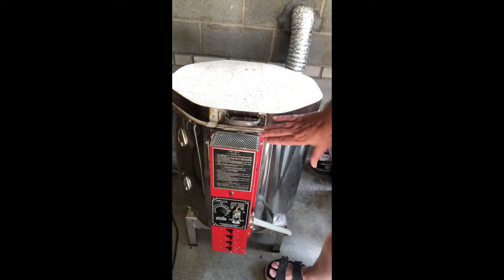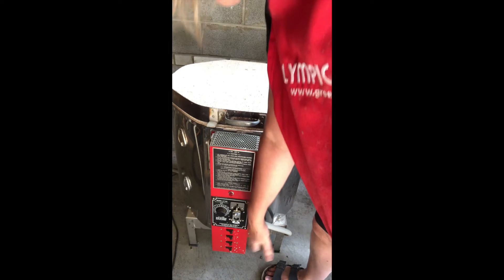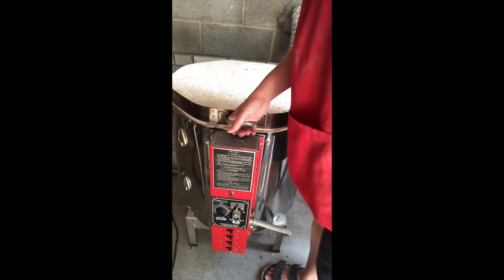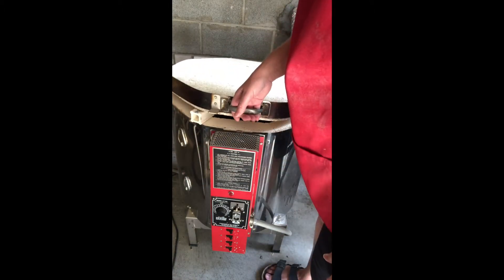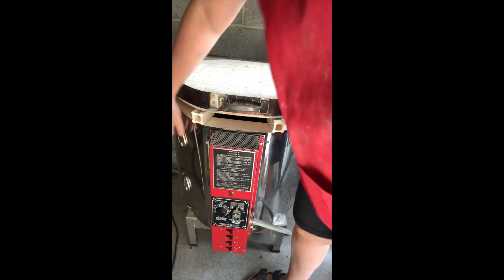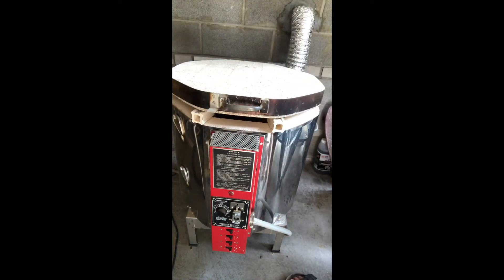So it is a safety switch. Now I am about to start it. On this kiln, the off side is on the right-hand side, so all the switches have to be in the off position. When you are doing a bisque firing — which is what I am doing — you want to have your kiln lid peeped open. I am going to do this right now, just so it is even on the back hinge. The other thing you want to do when you are doing a bisque fire is open up the peep holes so they are ready to go.